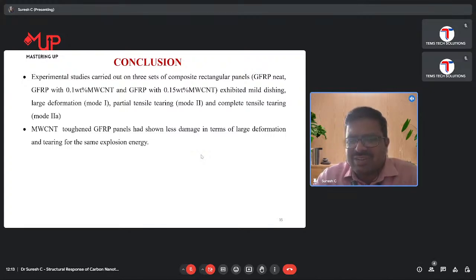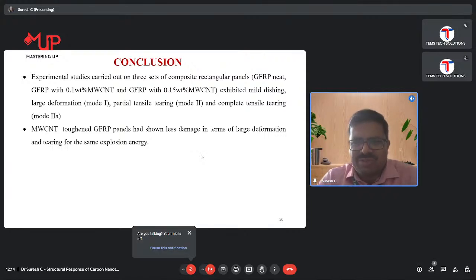From those studies we came to know that when it is air-backed, the damage is much higher, and when there is water behind the plate, the damage is reduced. It is because the shockwave traversing the water behind the plate gives stiffness to the plate, and it resists the deformation. When we add water behind the plate fully, the water is incompressible, so when the first plate deforms, it pushes the second plate also. If you provide some air gap between these two plates, that air gap is compressible. So the second plate deformation will slightly reduce, because the air will get compressed and the fluid will take some amount of the shockwave, and the second plate will not be exposed to much of the shockwaves. So this is our outcome of the studies overall.